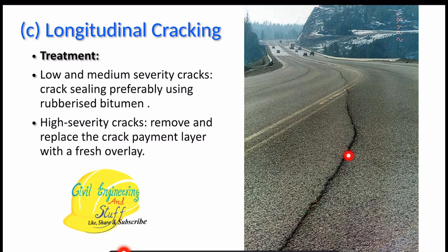Again, an example of longitudinal cracking. You can see this is hilly terrain, as we were discussing, and you can see this longitudinal cracking. So what could be a treatment for longitudinal cracking? If the crack severity is low to medium, we will try to seal the crack. If the crack is simply a hairline or up to 3 mm, we will seal it using some rubberized bitumen.